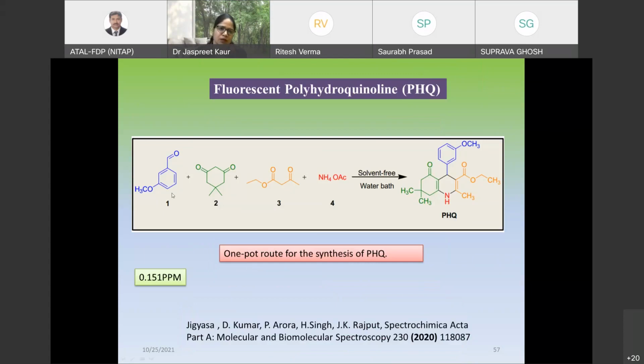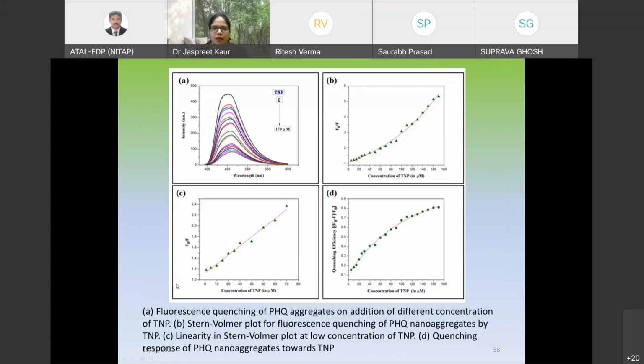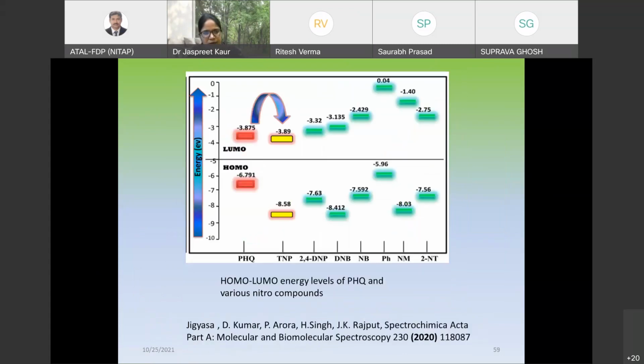Similarly, there is another class of compounds which are called polyhydroquinoline derivatives. These compounds have been synthesized in our lab by a one-pot, three-component or four-component reaction. It's a solvent-free reaction which gives the polyhydroquinoline derivative. You can see it shows a better sensitivity for detection of TNP, 0.151 parts per million, as compared to the previous one. Again, fluorescence quenching, you can see over here, the Stern-Volmer plot is there, which shows linear behavior at low concentrations. All these compounds again show the PET mechanism.